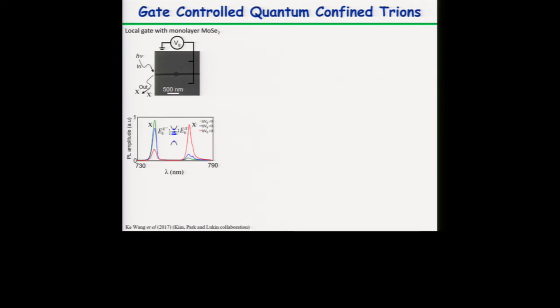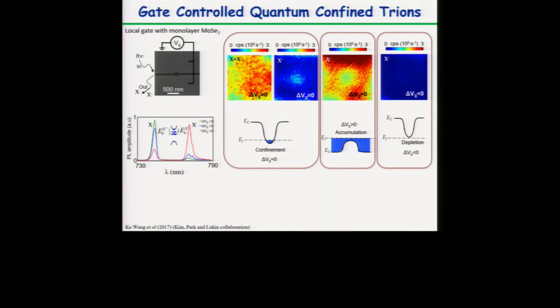This is something you cannot do that easily in gallium arsenide, at least not with gate control, because of the binding energy again. So the binding energy on a single layer, for the trion, is around 30 millielectronvolts compared to just a few millielectronvolts for a trion in gallium arsenide. Okay, so we can make this gate-controlled localized trions, right?